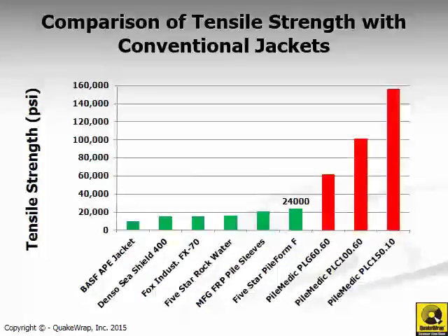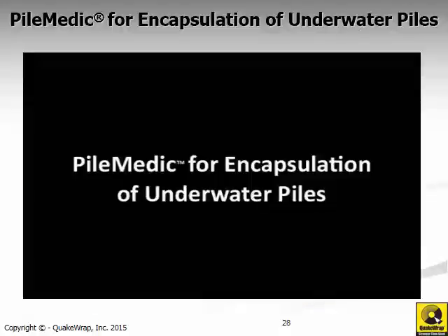In contrast, when you compare those to our PileMedic jackets, you notice that our weakest product has a tensile strength of 60,000 psi, and we can go as high as close to 160,000 psi. So these materials are truly a structural solution that is very strong, and we can also utilize the full strength capacity of these in our retrofit applications.